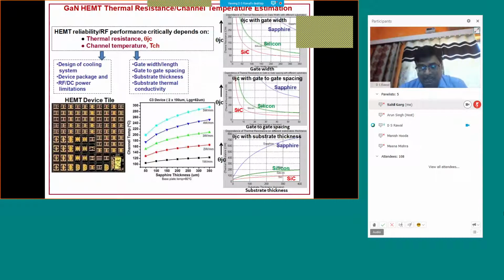So you can see that this graph shows how the channel temperature is varying with the kind of substrate. You can see that channel temperature is minimum for the silicon carbide substrate because of the obvious reason of having very high thermal conductivity of silicon carbide. So that is why this silicon carbide substrate is most preferred for these high power applications, because it can dissipate very high power at a very fast rate, and we can have high channel current, high channel temperature devices delivering very high power densities.